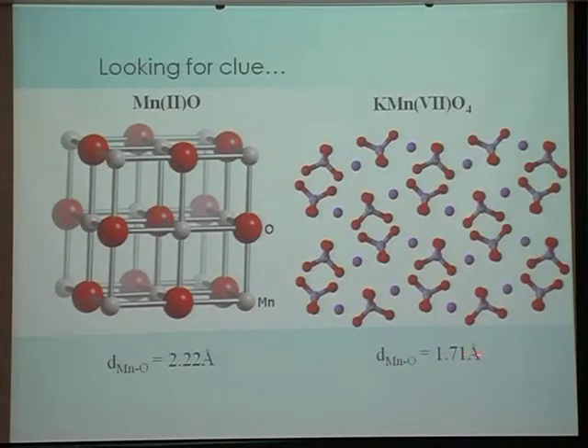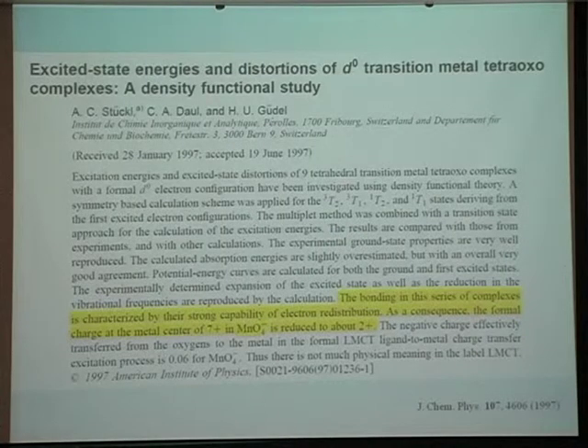MnO4 is 1.71 angstrom, while this one is 2.22 angstrom. A huge difference for the same manganese-oxygen bond. You can argue, of course, that the manganese oxidation states are different, but that probably does not explain such a large variation. In fact, certain theoretical work says this: the bonding in this series of